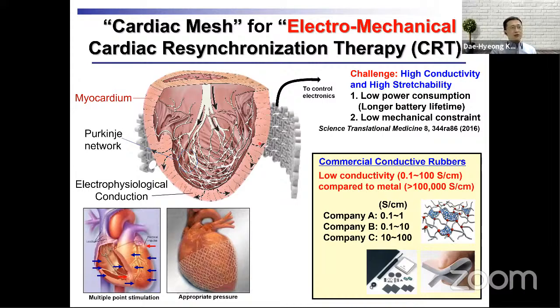But although the concept is unique, we had issues in materials. For your information, the typical conductivity of a metal electrode is higher than 100,000 Siemens per centimeter, although the commercial conductive rubbers show conductivity way less than 100. There is a big difference, and because of this low conductivity, in other words, high resistivity, high power consumption as well as delayed signal conduction can occur. So the first thing that we had to do is to develop a high conductivity rubber first to fabricate this device.